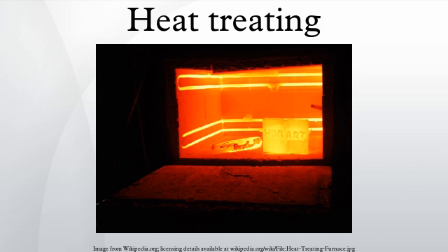Induction hardening. Induction hardening is a surface hardening technique in which the surface of the metal is heated very quickly, using a no-contact method of induction heating. The alloy is then quenched, producing a martensite transformation at the surface while leaving the underlying metal unchanged. This creates a very hard, wear-resistant surface while maintaining the proper toughness in the majority of the object. Crankshaft journals are a good example of an induction-hardened surface.